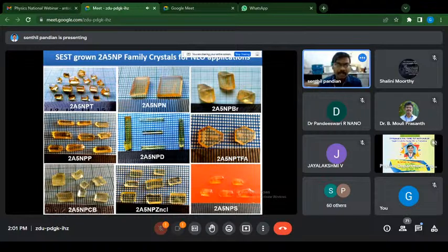So you see, from this SEST in a beaker, crystallizer or petri dish, this kind of very small size crystal can be possible. So we cannot grow the large size single crystals because of this method itself having some problems like high dislocation content, many milky opaques, micro cracks kind of things are always appeared in these conventional method grown crystal. But the SHG efficiencies, harmonic generation efficiency of some of these crystals are more than 30 times that of the standard potassium dihydrogen phosphate KDP single crystal.